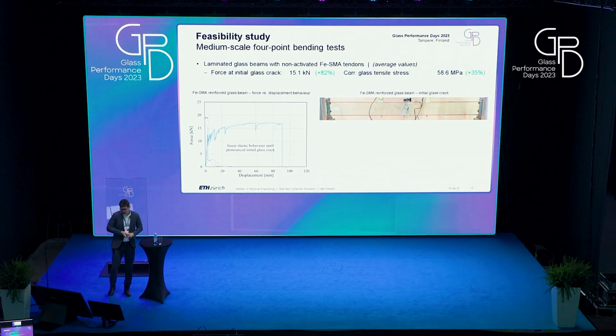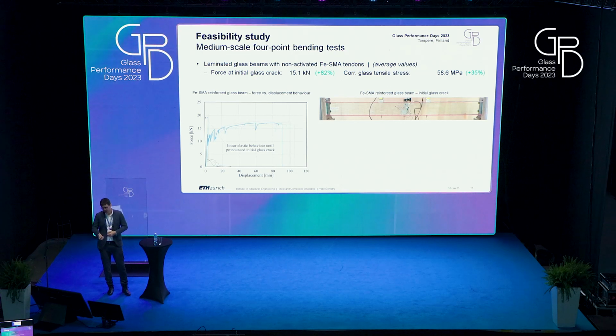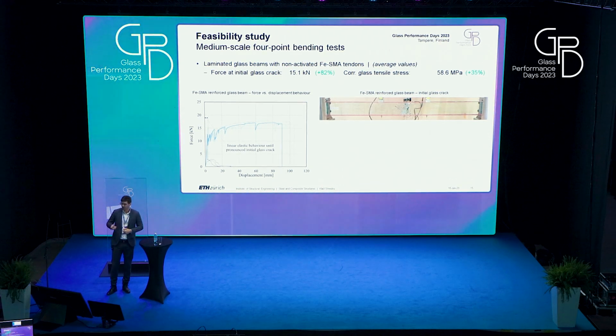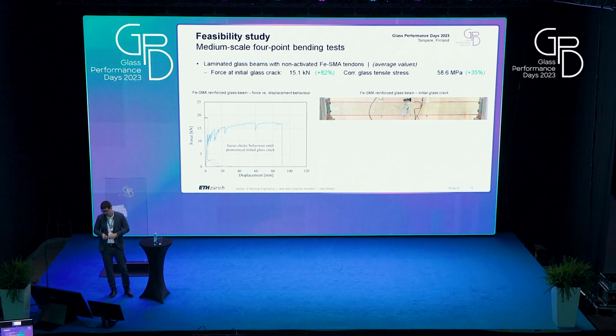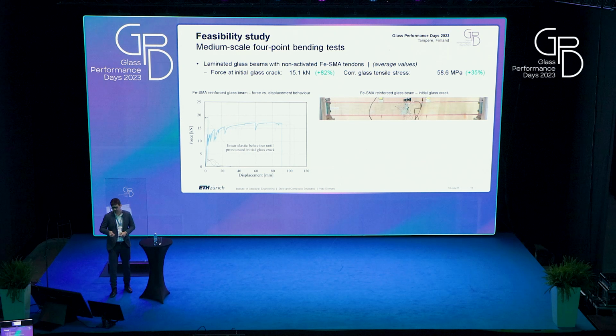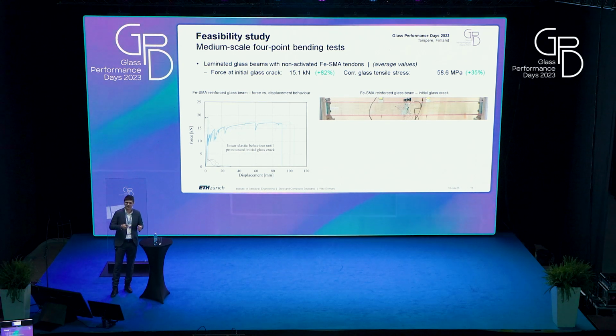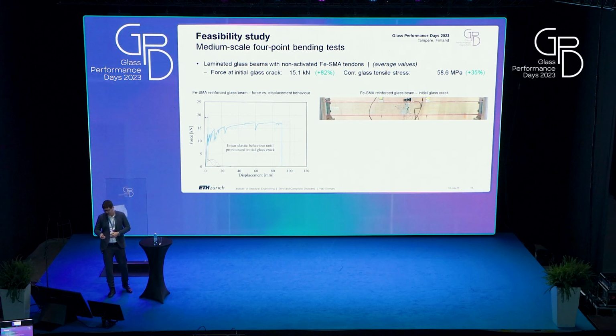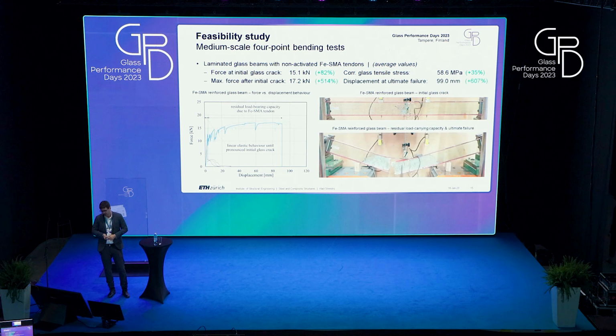For the reinforced beams, we were able to increase the initial glass crack force. These are the beams with tendons, but non-activated ones. So we were able to significantly increase the force at initial glass crack. And interestingly, we also had stresses when this crack happened quite significantly higher than the expected strength of the annealed glass.